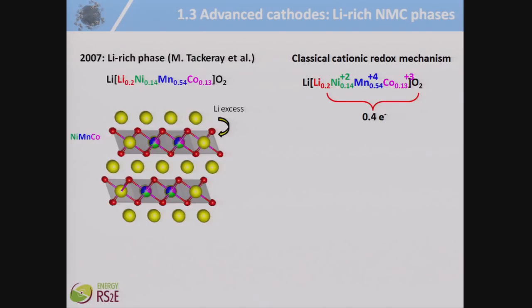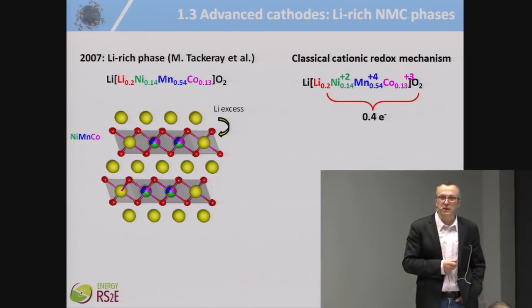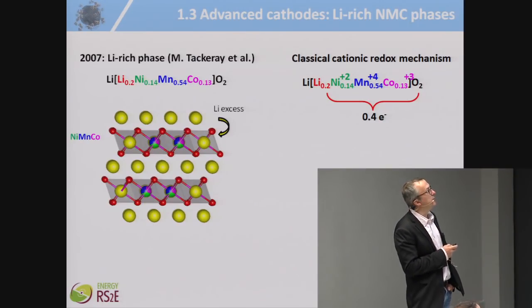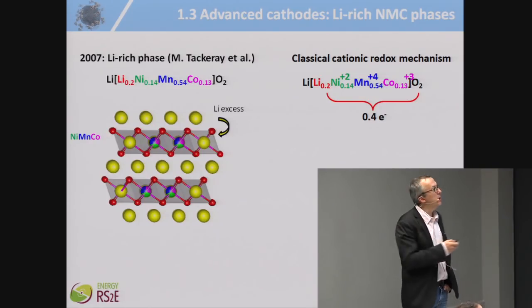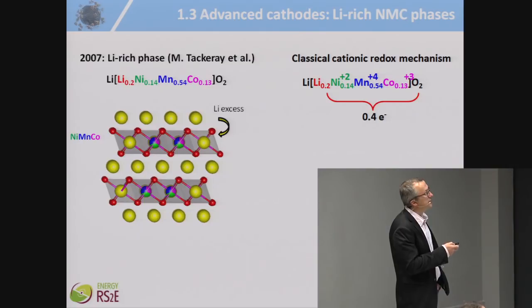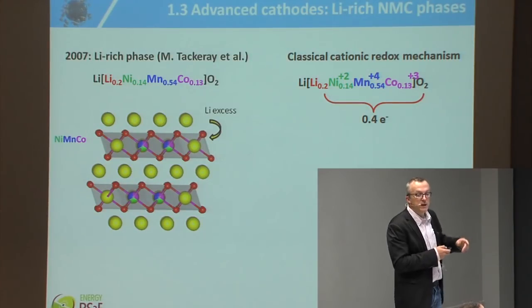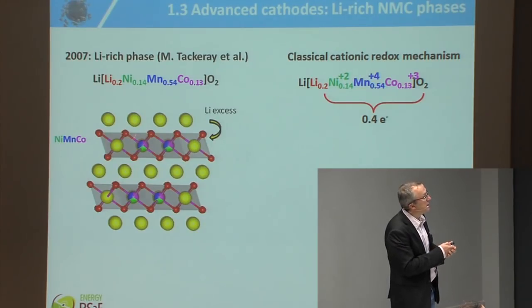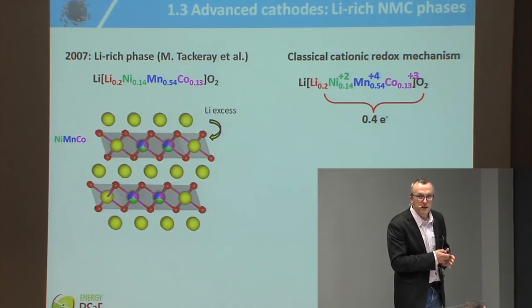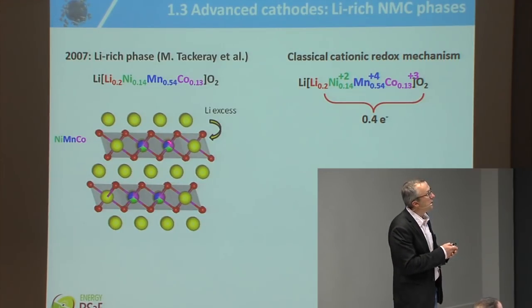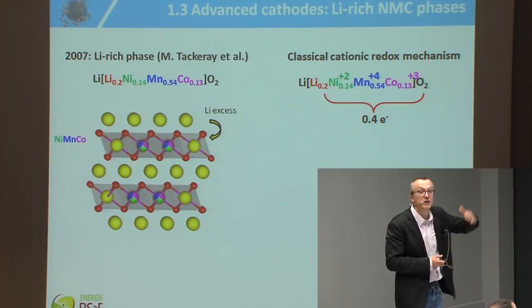Another key advance, which is very recent and not yet commercial, is the discovery in 2007 by Mike Thackeray in the US of what we call lithium-rich phase. NMC material, remember, you have CoO2 layers and lithium plus in between, okay? When you have NMC material, it means that the site for cobalt is shared between cobalt, manganese, and nickel. So you may have one transition metal in this site. In lithium-rich phases, on the site of a transition metal, you put a lithium plus, and then you have an additional lithium in the structure. So that's a way to increase the capacity.